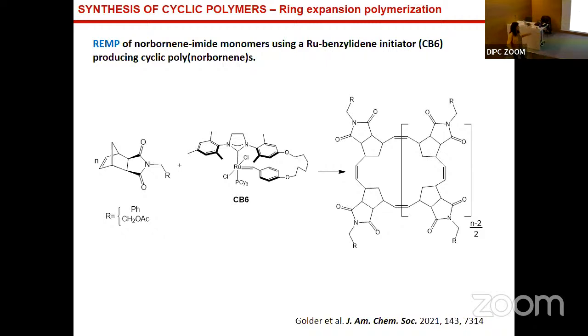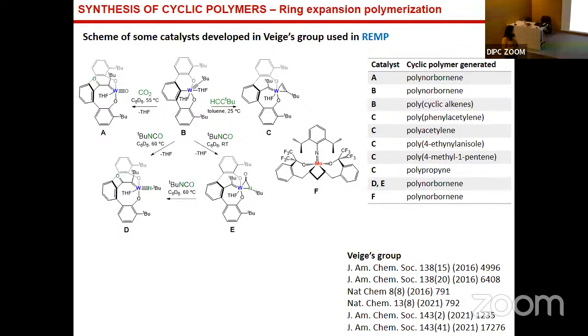As you see, over 20 years, there have been more and more examples and approaches to synthesize a nice cyclic polymer. The catalyst design is also very important here in the synthesis of cyclic polymers. These are tungsten catalysts developed in the group of Veige in a university in Florida, where they demonstrated that they just modify the linker here. In this case, they modify the linker, and they are able to obtain cyclic polynorbornenes, polyacetylene, etc. These are the very important papers from the group, where they demonstrated the development of this catalyst and the generation of the cyclic polymers.